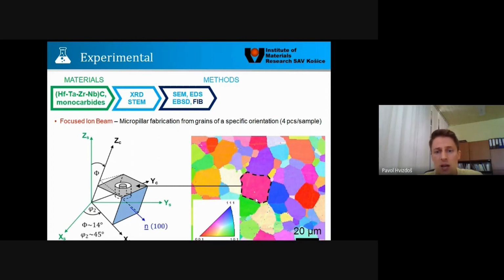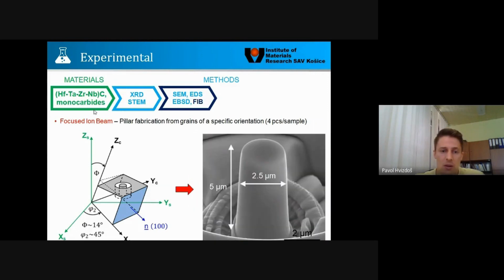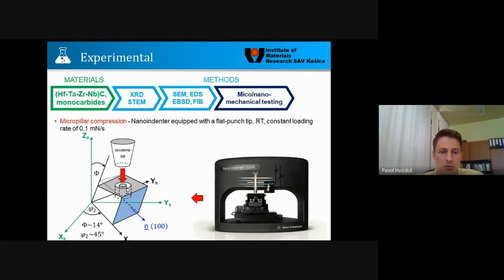So from this grain, or that kind of grains, we prepared 4 micropillars, not only in the high entropy carbide material, but also in the monocarbides, because we wanted to compare the deformability of that newly synthesized material with the base monocarbides, just to be able to see what is the difference compared to them. The as-fabricated pillars are shown here with a size of 2.5 micron in diameter and 5 micron in height. And those pillars were used for compression. We used the nano indentation machine equipped with a diamond flat punch tip used for compression using a constant load rate at room temperature.